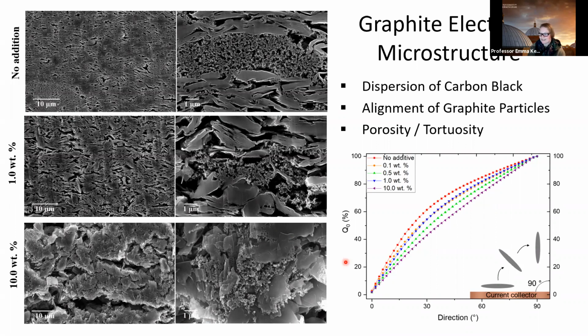production style electrode. Because without a doubt, we have porosities in this of round about 50–60%, which is far too high. It needs to be down to 25–30% for a graphite electrode, really. And the calendaring kind of destroys the microstructure, and it doesn't make such a nice picture. So yes, we'd still need to find some ways of improving that.